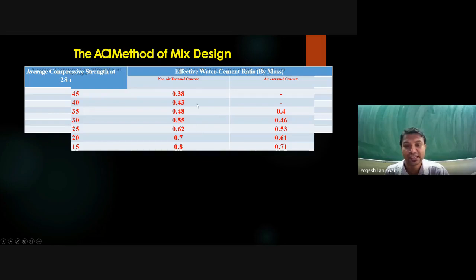Likewise, you can see in this particular table, for the 15 grade of concrete, for average compressive strength at 28 days for 15, there is a water cement ratio. For non-air entrained concrete it is 0.8, whereas for air entrained concrete it is 0.71.